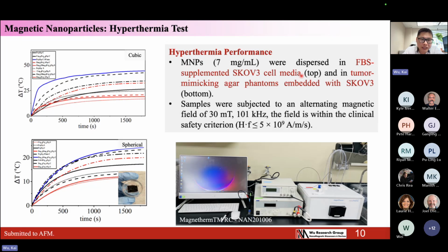Then we incubate these particles with this liquid medium, in the top figure. We also incubate the particles in an agar phantom embedded with the tumor cells. This agar phantom is a mimic of human tissue, which is a solid structure, as you can see from the photo here. So in the agar phantom, the Brownian motion of the nanoparticles will be blocked. So the hyperthermia heating will be produced by the hysteresis loss of the particles through the Néel process.